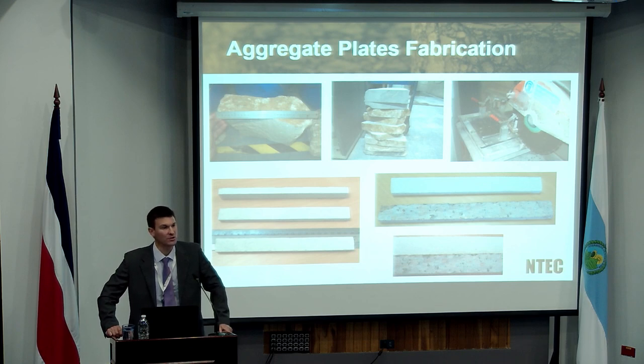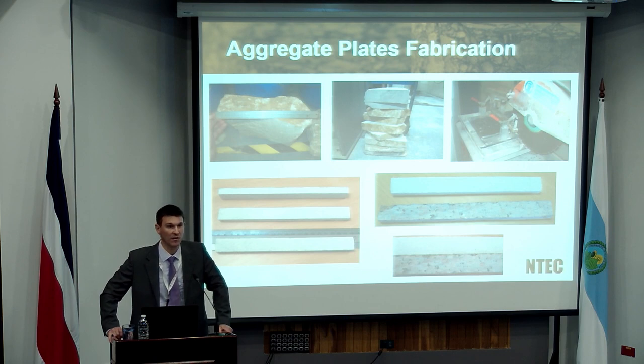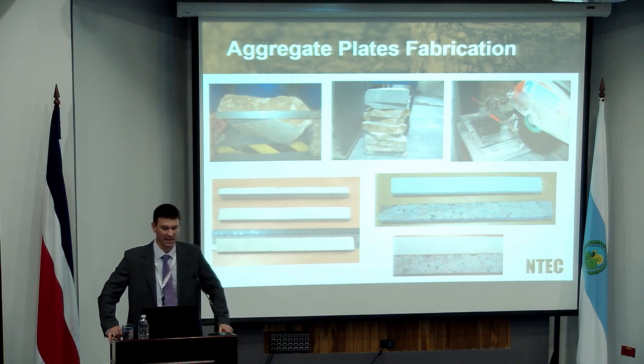So the process that we've used was to obtain boulders, effectively from the same quarry that we would produce in terms of our asphalt aggregates. We would obtain boulders that were used or produced before they were crushed into the aggregate. We would go through quite a complicated regime in terms of cutting and sawing to make sure that we ended up then at the bottom of that particular slide with effectively cubes of nicely positioned substrate aggregates. So dimensions were roughly 200 millimeters in terms of the longest dimension, 20 millimeters in terms of the cross-sectional area.